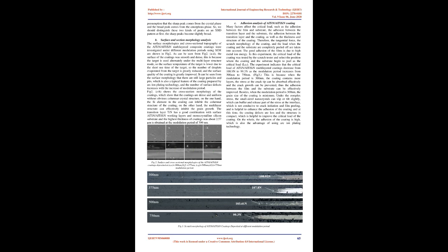The high temperature friction and wear tester, Anton Paar, was used to test the average friction coefficient of the film at room temperature. An Al2O3 ball was selected as the wear pair. The applied load was 2 N, the radius was 8 mm, and 2500 cycles were set. The average value was taken 3 times for each coating type experiment.